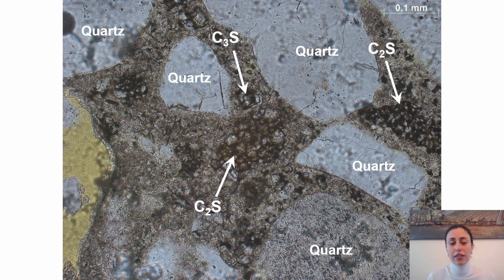That of course asks for explanation, and the explanation lies in the morphology and in the composition of the old cement paste. In the Netherlands, in the past, we used very coarse cement. As you can see, here are clusters, or let's say grapes, very familiar to all of us, of cement clinkers. And these clinkers cannot react in the conditions studied here, at a temperature of 20 degrees Celsius. What can react are the cement hydration products, but only if they are thermally reactivated. So to conclude, the recycled sand studied here doesn't show any reactivity, and this is due to the coarseness of the cement that was used in the past.